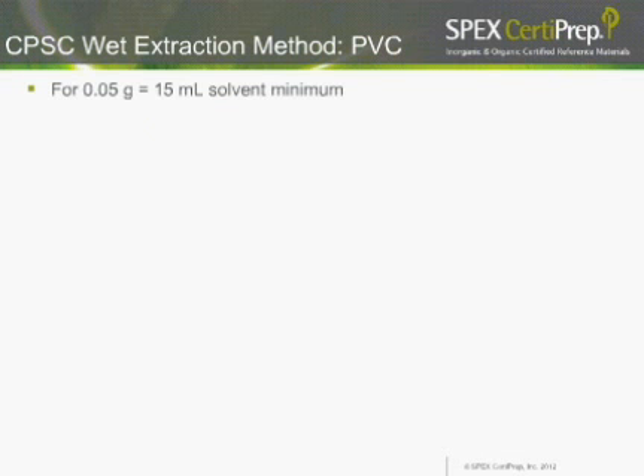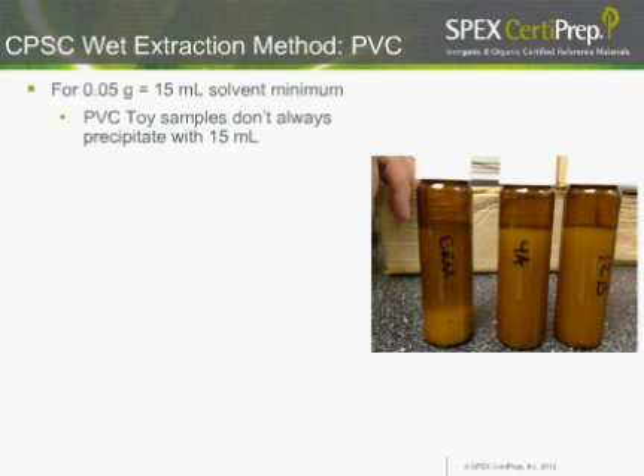For this method in general, you use about 0.05 grams of sample to about 15 mL of solvent minimum. But what we found with our PVC toys is that they don't always precipitate with the 15 mL of solvent. What we have here is a picture of 3 different vials. On the left is our CRM material, which does not contain anything but 6 of the restricted phthalates. It doesn't contain any colorants, any binders, or any other types of material which might be added to a PVC toy. On the right are 2 PVC toy samples. When we added our 15 mL of solvent and we tried to precipitate out our PVC material again, we were unable to get the PVC to fully precipitate out of the solution.